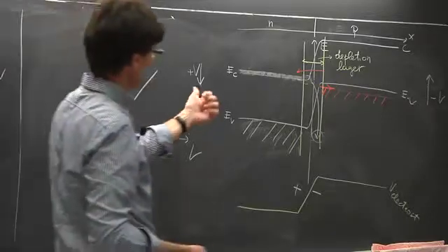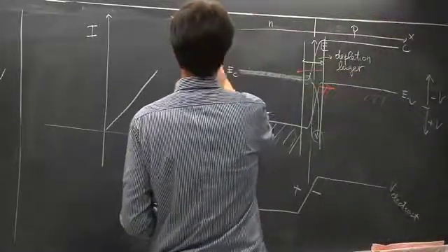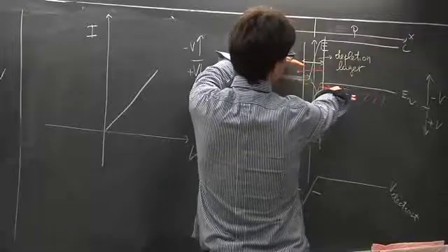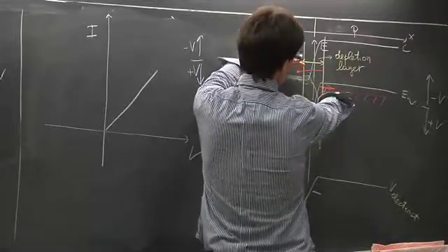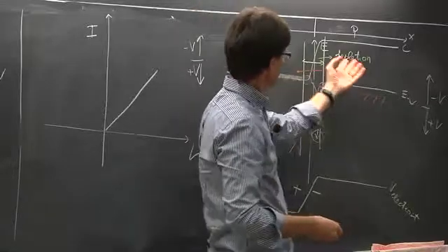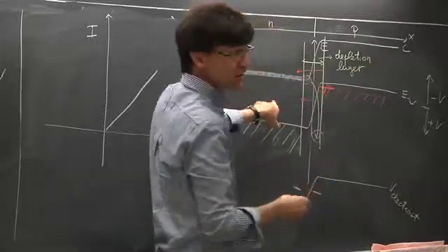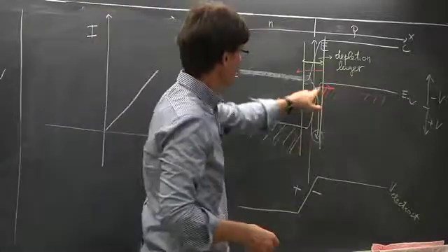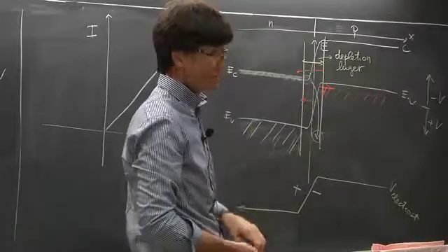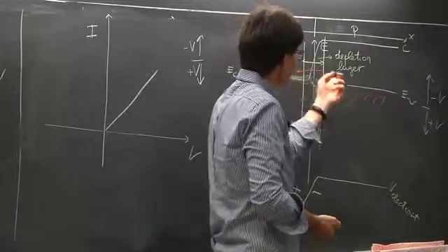The interesting part is the other one. It's when I lower here the potential, so apply a positive bias here and a negative bias here. Because if I do this, I'm lifting this band with respect to this one, right? And you see there's no chance for electrons to flow any longer, because I have a very small amount of electrons here, but then this is very small. These electrons here, they won't be able to flow any longer because there are no available states on the left side to flow into. Not even at lower energies, because these states are all filled. The first available states are above. Right? I could, in principle, transfer these states here, but then, first of all, it's a small number of electrons. And second, they have to cross a barrier to go to the other side.